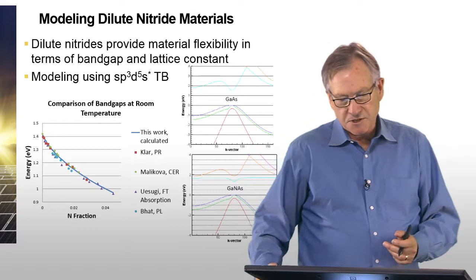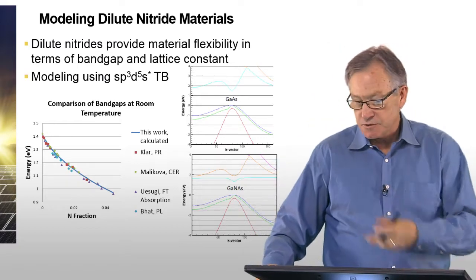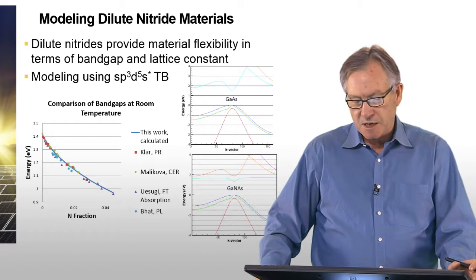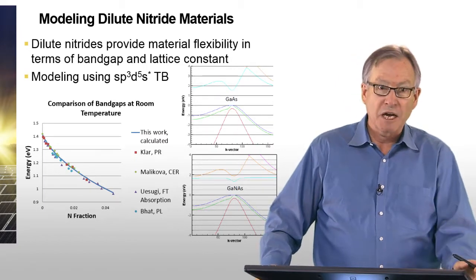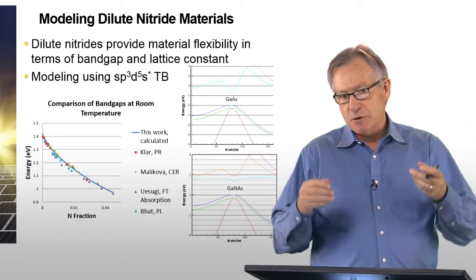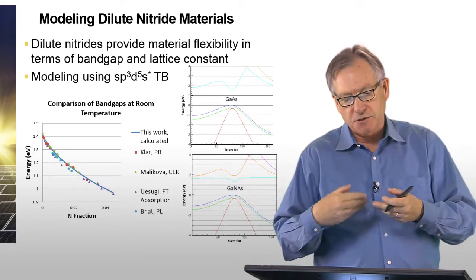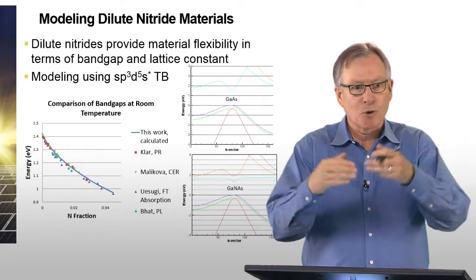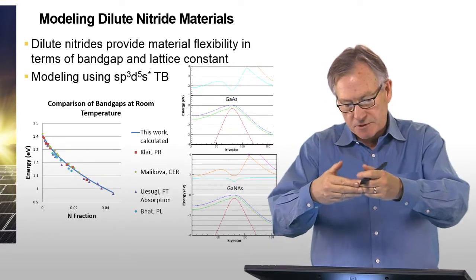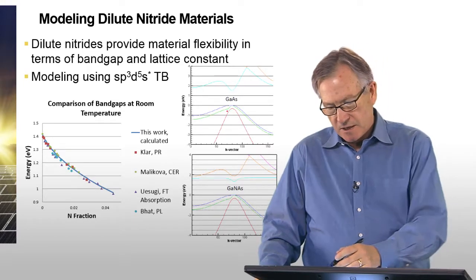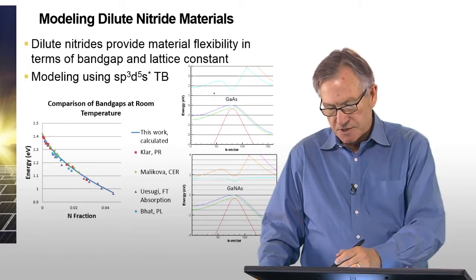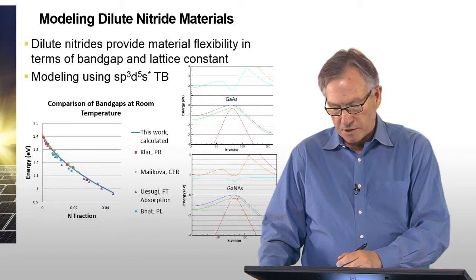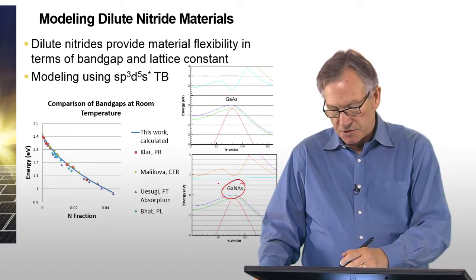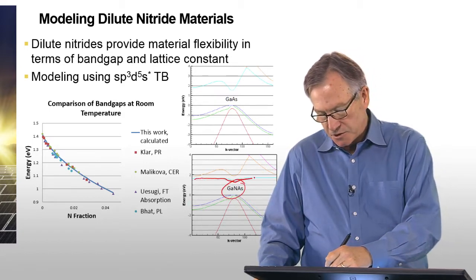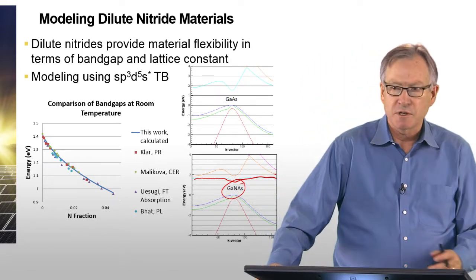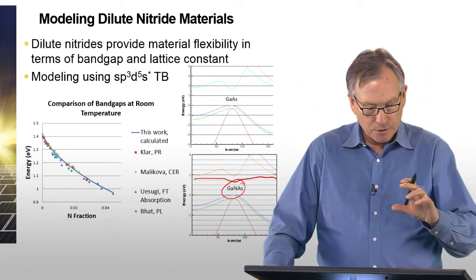And we use different approaches for calculating the electronic structure. Right now, we use, for example, what's called sp3d5s star tight binding, which is an atomistic way or molecular orbital way of calculating the electronic structure by looking at the overlap of atomic orbitals to form the semiconductor band structure. And this is calculations showing, for example, the effect of nitrogen. So this is gallium arsenide, and this is gallium arsenide with a dilute quantity of nitrogen. And you can see that it introduces an additional level, which introduces a lower band gap, so it makes the effective band gap lower.